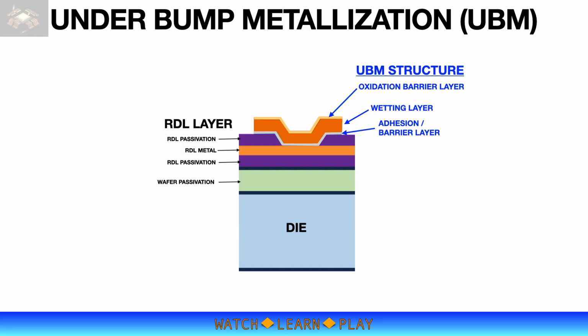Flip chip reliability is anchored on the integrity of the solder joint between bump and UBM. A weak solder joint will ultimately result in device failure. The UBM structure has several layers and must be compatible with bumping technology. Typically, the first layer is at the bottom and connected to the RDL metal. It is the adhesion layer and also acts as a barrier layer. The next layer is the wetting layer, and finally, the oxidation barrier layer.